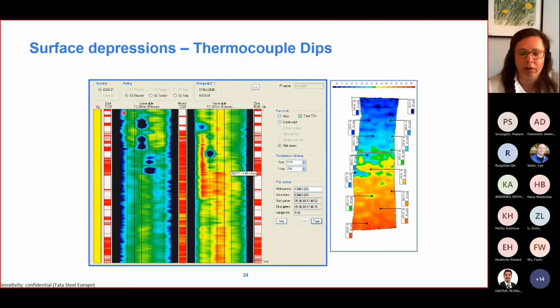This is a temperature image of thermocouple lines where the dark patches are shrinkage. The steel shell has been shrunk and detached from the mold. So if the steel shell shrinks and detaches from the mold, what happens? It doesn't extract its heat. If it doesn't extract its heat, it cannot solidify or further solidify. So it cannot further grow as a shell. And thus, also associated to that, because here it has another temperature than here, we will also have thermal stresses, very local, between this area and the other area which is attached to the mold, or is touching the mold. Because it detached, it cannot solidify properly.